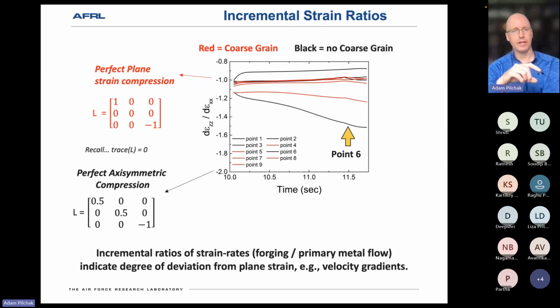Perfect plane strain compression means that any strain I put in along the forging direction, Z here, must be balanced by strain in the primary metal flow direction, X. So in the very center of the bar, where there's no movement of that material element axially along the bar, you have a state of perfect plane strain compression. On the other hand, if we think back to my axisymmetric upset tests, they have a strain path that's represented by this.